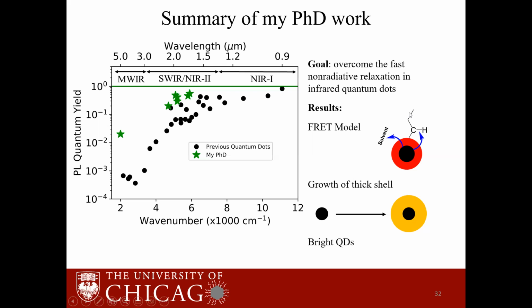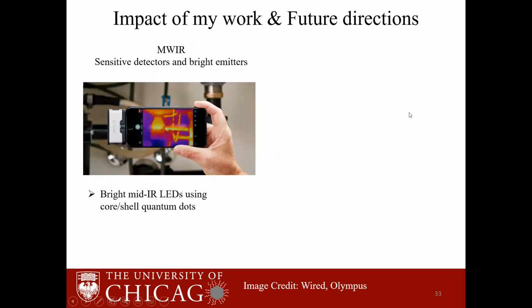So I want to discuss one slide on some future directions that are possible. Our growth of robust shells around mercury selenide quantum dots can be used to make bright LEDs. And this is something that we are doing in our group right now. An eventual ultimate goal is to completely replace the organic ligands and put the quantum dots in an inorganic matrix so that there is no infrared absorption. And this is something which hopefully the next student will do. But this will be the way to get sensitive thermal cameras which have a slow non-radiative decay.